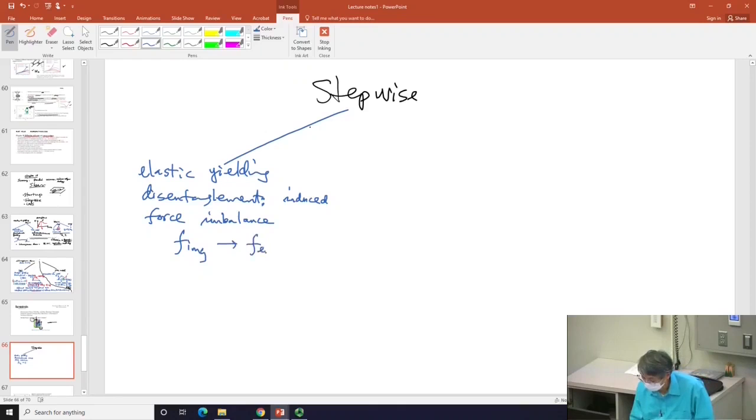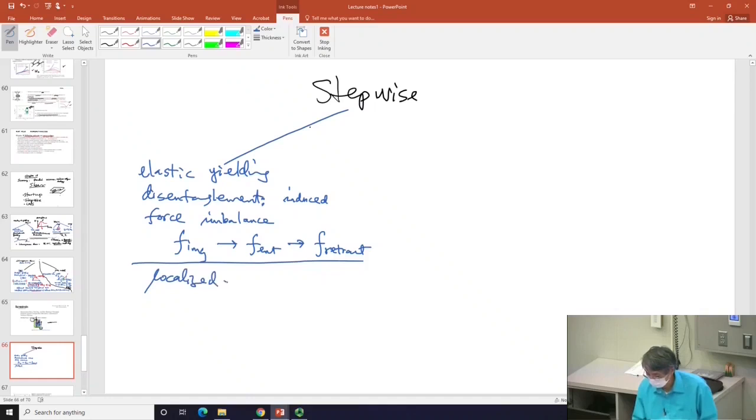And what's left is only a level of cohesion force that is fighting with a large amount of retractive force that you already built through an affine-like deformation. So this imbalance will cause the structure to fall apart by the path of disentanglement. And then if this can occur in a localized manner, then you have disaster. You have non-quiescent relaxation.